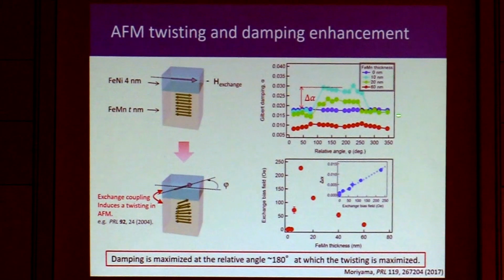So as you can see, at some iron manganese thicknesses, we have enhancement around 180 degrees, where the twisting is maximized. So when we take this delta alpha here and compare it with the exchange bias field, the iron manganese thickness dependence of the exchange bias field, actually this delta alpha is linearly correlated with the exchange bias field. So this means that the more exchange bias field you have, the more delta alpha, the enhancement of damping, which is consistent with the spin torque picture.